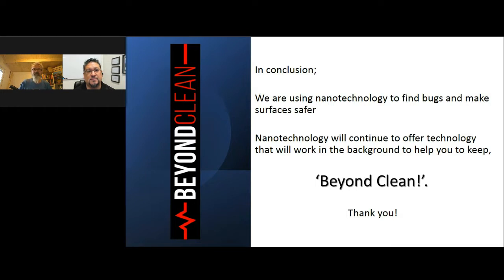But as I mentioned previously, the coating we have does not comprise nanoparticles on a surface. We've taken a flat surface and nanotextured that surface to give us the feature size we want, to give us the kill we want. So there are no nanoparticles on the surface, and there will be no release of nanoparticles from the surface. Very good. I said it was the last question, but it's not. I did get a couple more here.